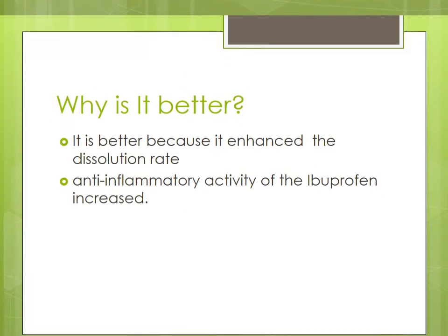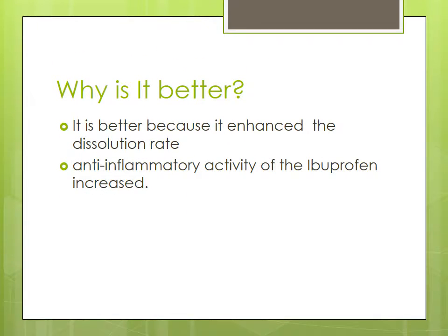Why is it better? According to the study, adding PEG to the ibuprofen increased the dissolution rate of the ibuprofen. It is stated that this might be due to the formation of microcrystals and the increase in the dispersibility and wettability of the PEG 8000. It also helped with the anti-inflammatory ability by having 90% edema inhibition, while ibuprofen alone has 77%.